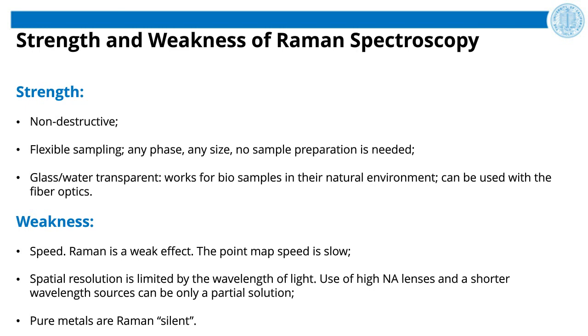For the weaknesses of Raman, we can probably mention that the Raman effect is very weak. So it requires time to collect the signal, and for instance, when we need to perform mapping or imaging of the material, it might take a long time. A partial solution can be found by using streamline mapping. However, it does not completely satisfy researchers. One of the possible solutions might be to couple Raman with SEM, which basically provides instant imaging.